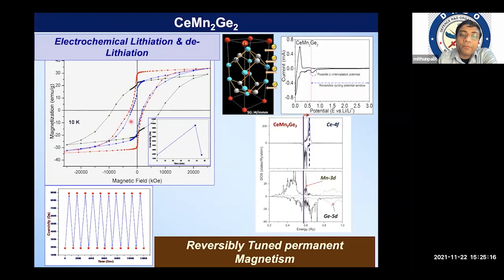And then the moment we charge it with lithium ion, a very tiny 0.1 mole fraction per mole of this compound, you can see the mammoth jump in the coercivity to almost 10,000 Oersted. That is 1 Tesla. So from 2000 to 10,000. And then the moment you take away the lithium by reversing the potential, it comes back to the original coercivity.